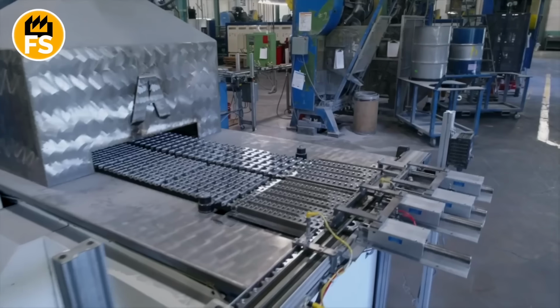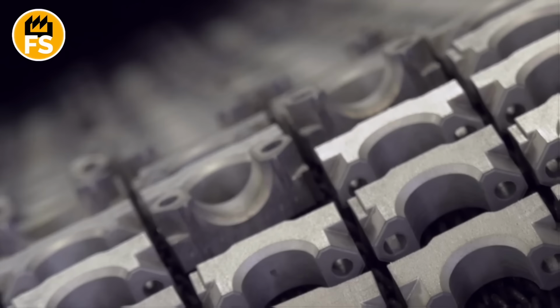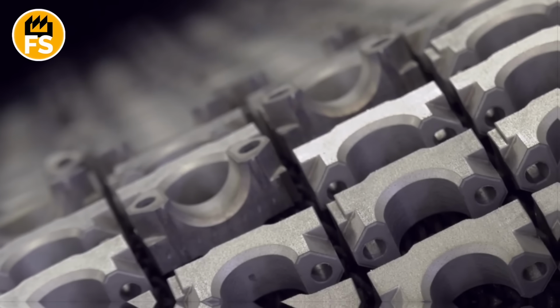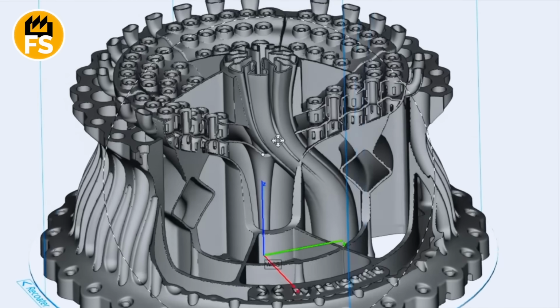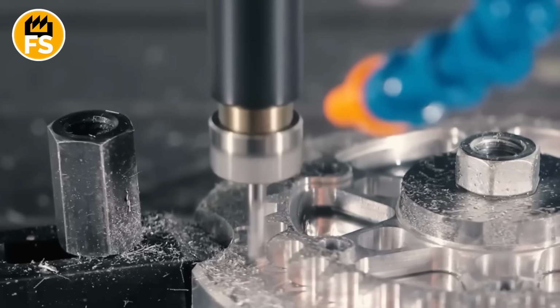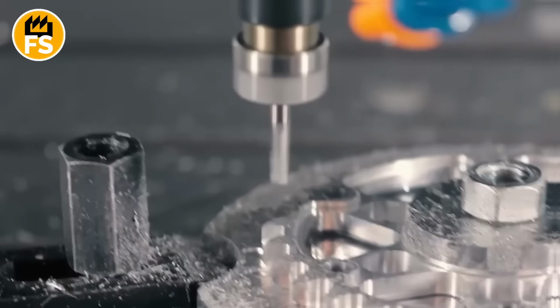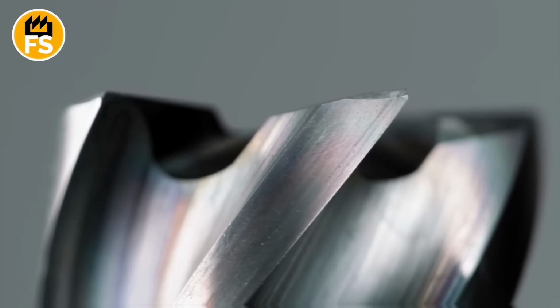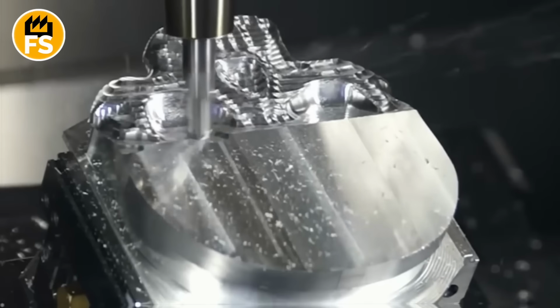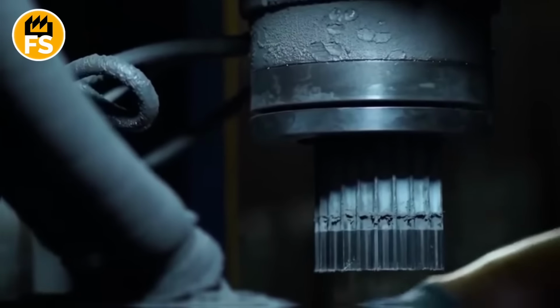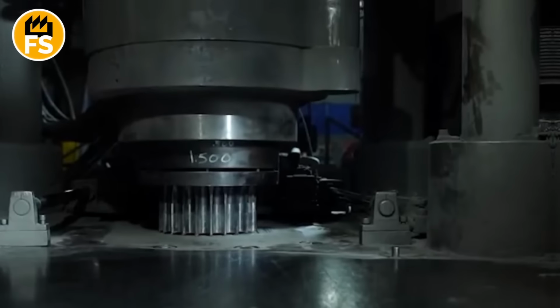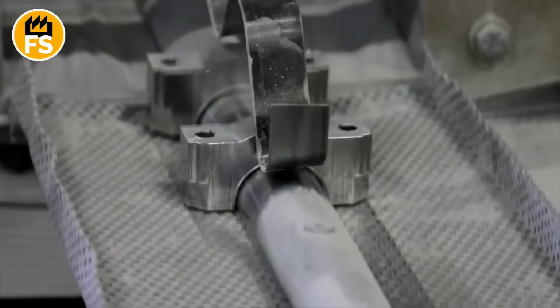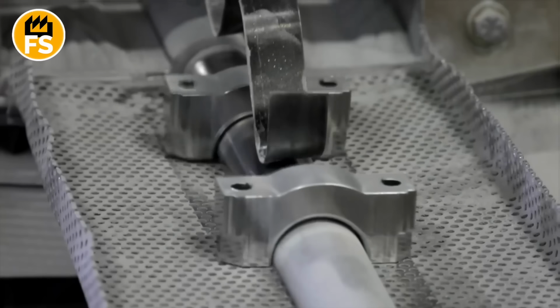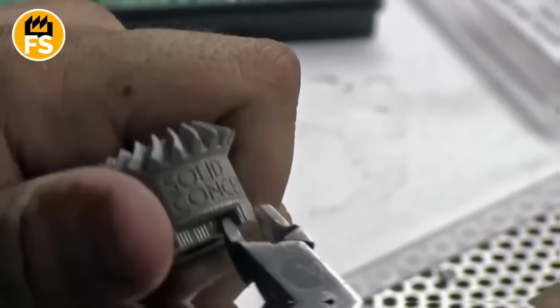You end up with a part that has properties impossible to achieve any other way. Super strong, ultra dense, with precise dimensions. The beauty of powder metallurgy is that you can make complex shaped parts with virtually zero waste. With traditional machining, you cut the desired shape out of a metal block, and up to 70% of the material ends up as chips. Here, the powder is poured precisely into the mold of the future part, sintered, and that's it, minimal scrap. After sintering, parts often require minimal additional machining or none at all.